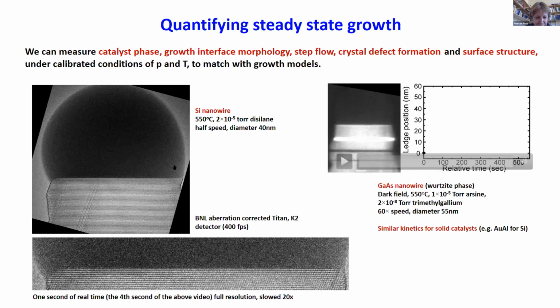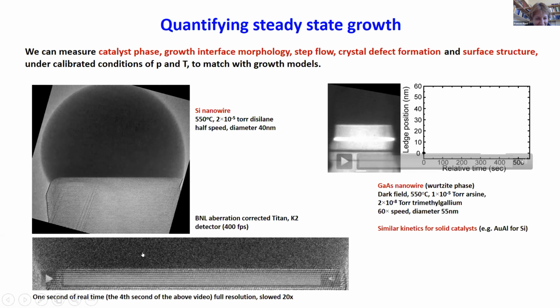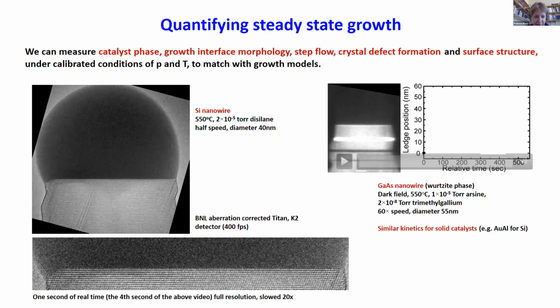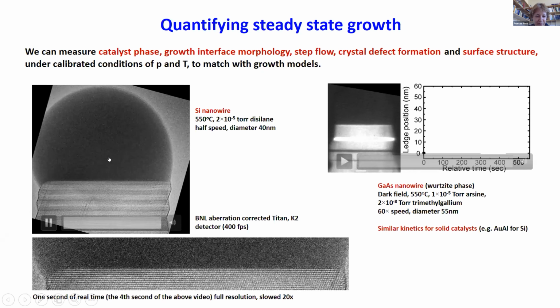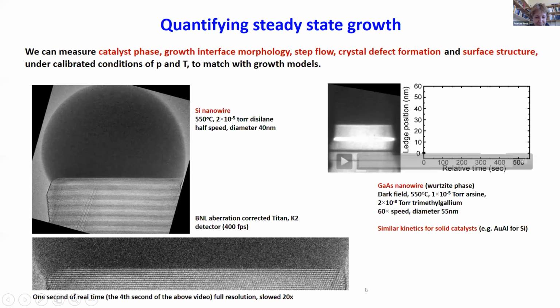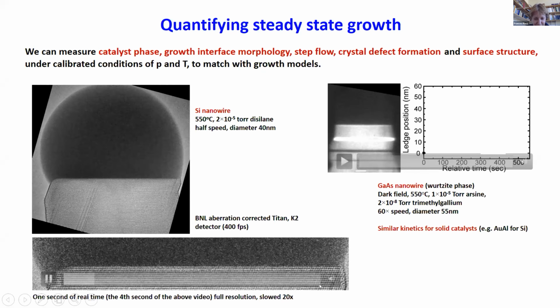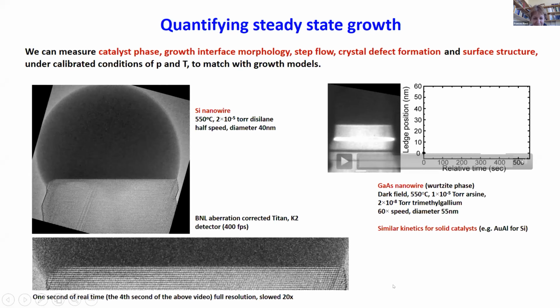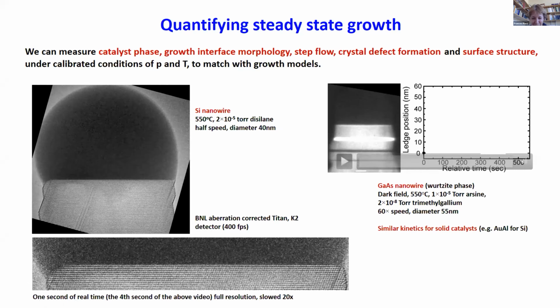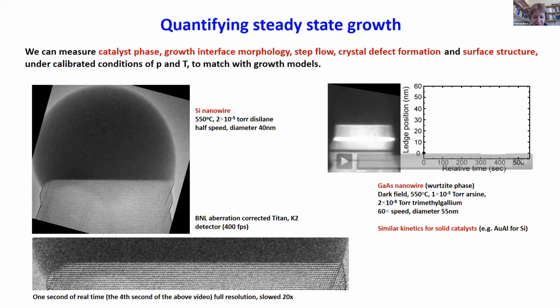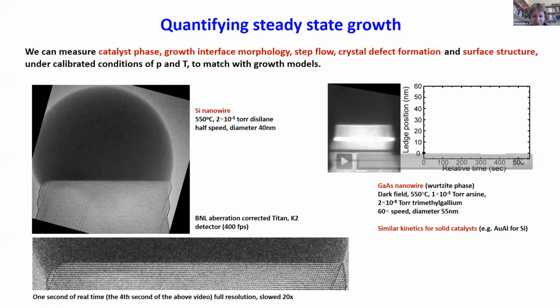So this movie that I'm going to show first is a high-res image of a nanowire growing. This one was actually recorded at Brookhaven using the environmental TEM. And you can see in the movie that the growth is taking place by little jumps, right? You see that the corner has little jumps and the motion of the growth interface has little jumps. Now, what if we cut out this section of the video and we expand it and we play it a bit slowly so that you can see how it goes. So here it goes. And did you see that? A single jump. And if we wait and wait, and there, another jump, another sheet of silicon atoms was added onto the growth interface. And it continues in this way as little jumps during the growth of the nanowire.